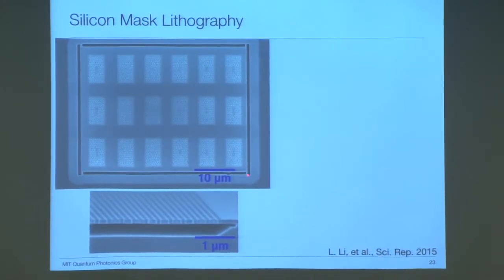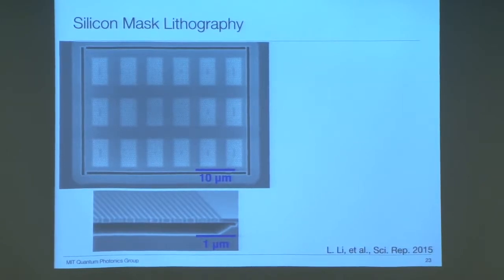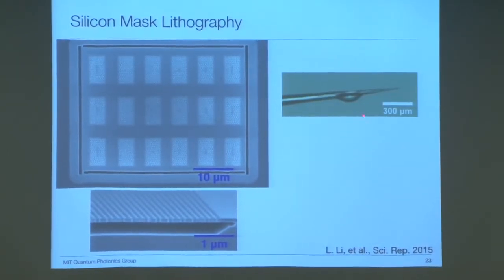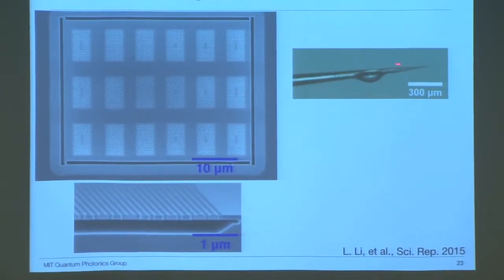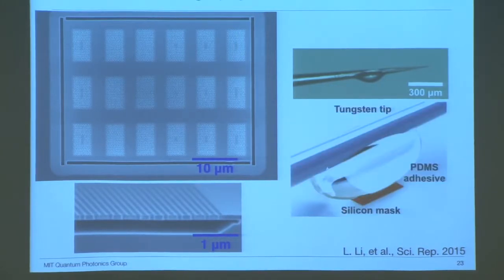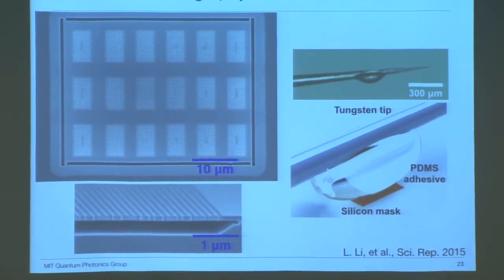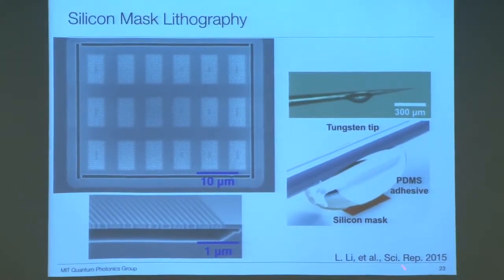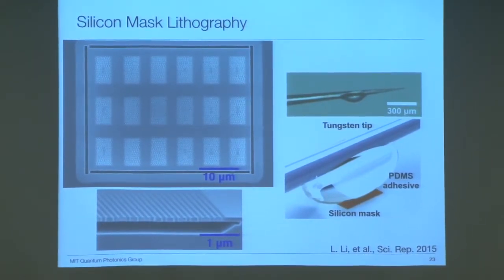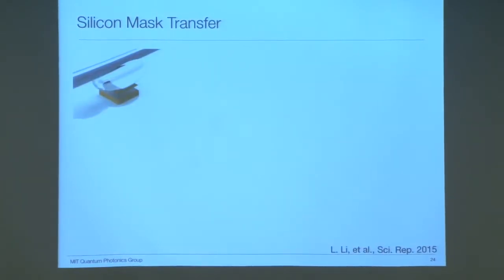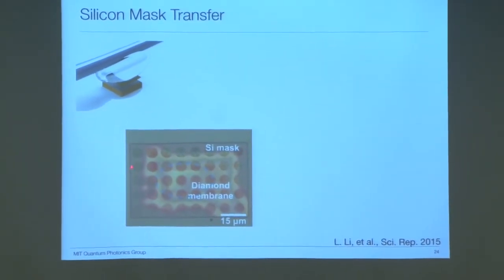These membranes are attached to the bulk substrate by these bridges at four corners. These bridges are easily broken if we touch the silicon mask with a PDMS adhesive attached to a tungsten tip. Adhesion between PDMS and silicon mask is strong enough that the silicon membrane is ripped from the parent chip. This is a PDMS adhesive with an attached silicon membrane. Then we release the silicon membrane onto a diamond membrane by rolling over the PDMS and then lifting the PDMS back up. This is an optical image of a silicon mask on top of a diamond membrane.